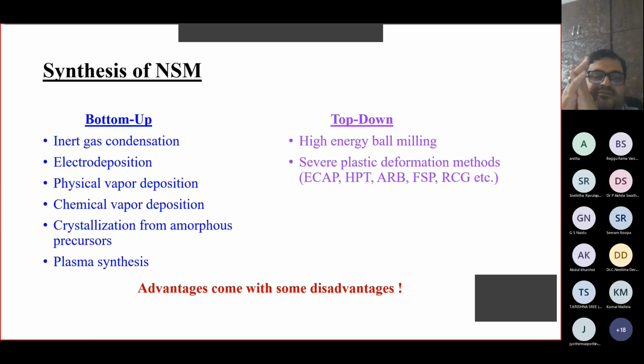And there exist several ways to develop these nanostructured materials, and based on the sequence in which they are grouped together at atomic scale, two schemes have come into existence. One is the bottom-up approach, the other is the top-down approach. In the bottom-up approach, the processes include inert gas condensation, electrodeposition, physical vapor deposition, chemical vapor deposition, crystallization from amorphous precursors, plasma synthesis, and so on. So in all this bottom-up approach, you start with atoms and then build the structures atom by atom. You come from the bottom to the top. So that's why you call it the bottom-up approach.